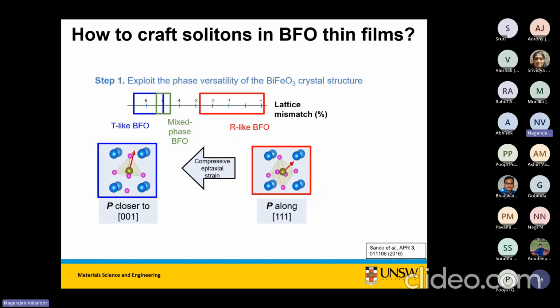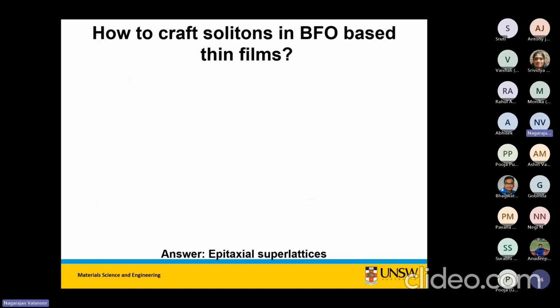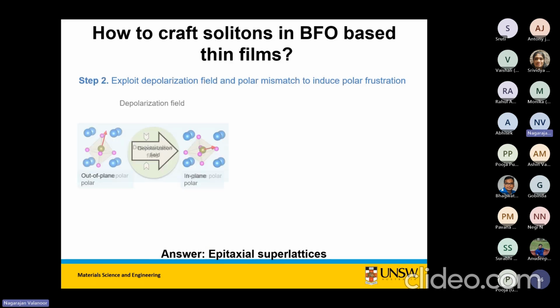But we want it to form like a curling structure, right? How are you going to get that to happen? You exploit the fact that when you grow it very thin, the polarization cannot be sustained, and the system is going to try to kill the polarization. So that means the depolarization field is going to try to make the system go from out of plane to in plane.